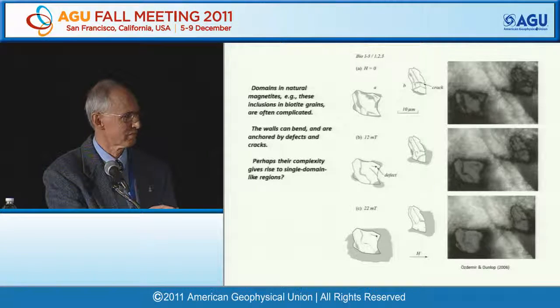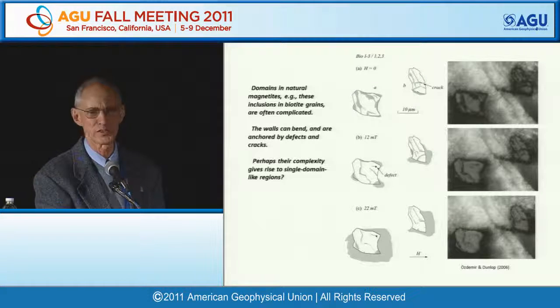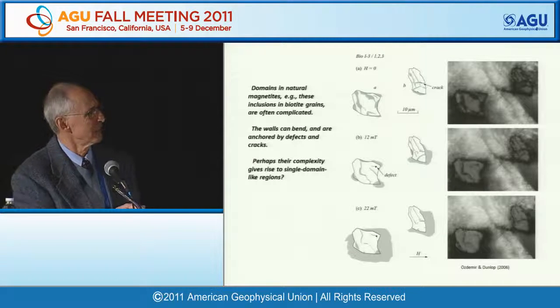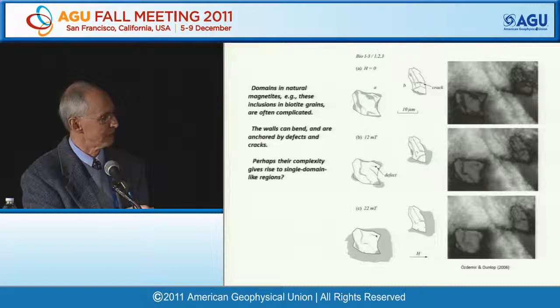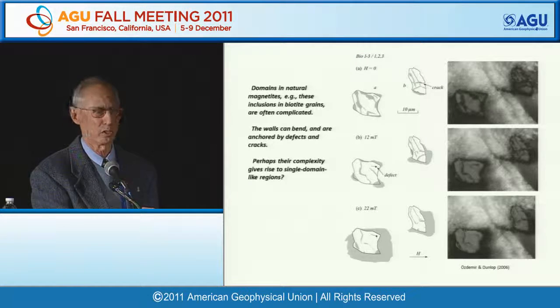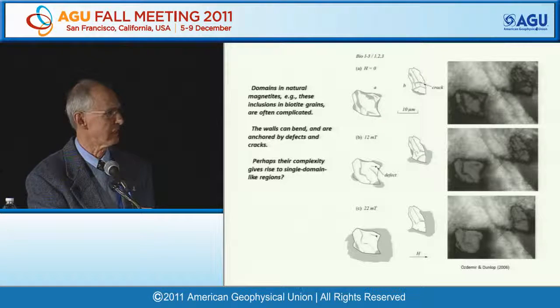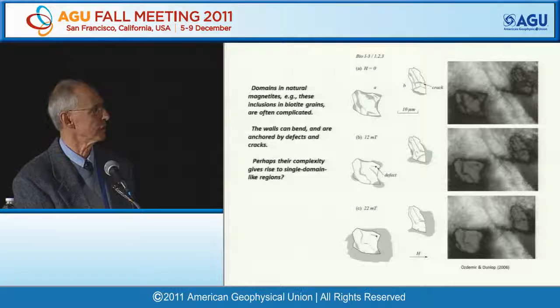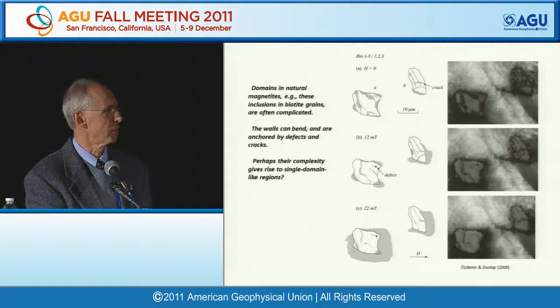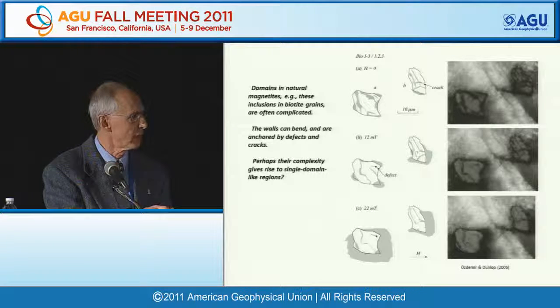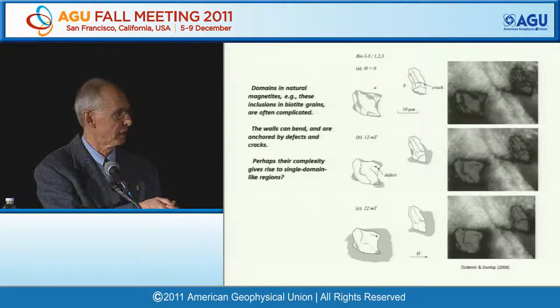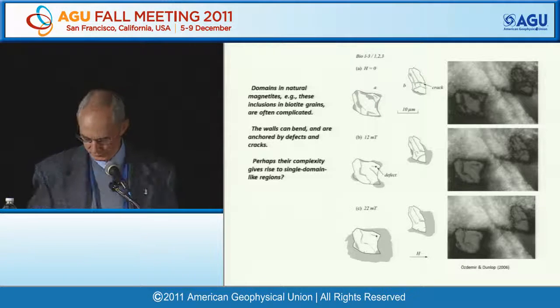And I think Usden and I are just as proud of these results as we are of the textbook examples. They show that domains in natural magnetite, these are inclusions in biotites, do strange things. The walls bend, which they shouldn't do. Magnetostatics says they can't do that in a strongly magnetic material, but they do. They're anchored strongly by defects and cracks. This wall is bending, this wall is pinned at a defect. The walls here are so strongly affected by the crack that even by applying large fields, they don't move. The ones that are loosely pinned, they move easily.